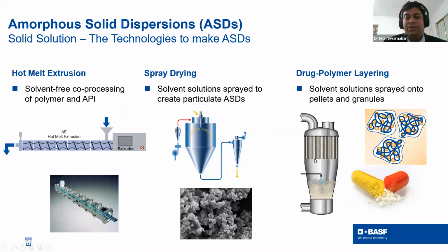It's very simple. You need to take non-pareil seeds. You dissolve your drug and polymer, and then you spray. And then what you're going to see is sometimes the polymer will come on. It's like more granulation if you do the top spray. If you do the bottom spray, you can see more Wurster coating where individual seeds get coated with the polymer and drug. So this is the difference between top coating and bottom coating. And you might have tangential coating also, which is generally a modification of this kind of technology.